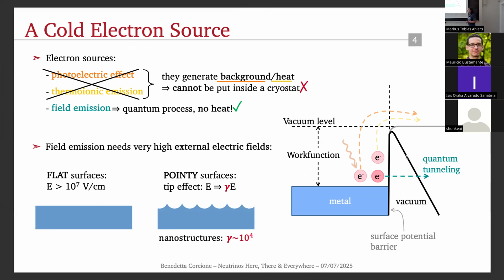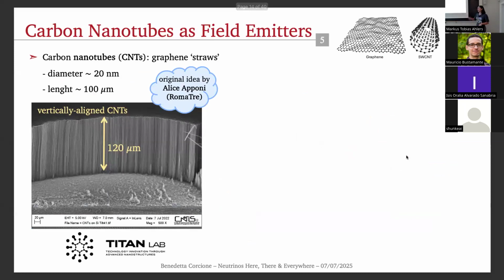So in particular, if we want to extract electrons from a flat surface, we need fields higher than 10 to the 7 volts per centimeter. But if we use pointy surfaces, so surfaces with some nanostructures, we can have some local field enhancement factor due to the tip effect up to 10 to the 4. And this is precisely the trick we use, because like that we can extract electrons with much lower electric fields. And the nanostructures we decided to use as field emitters are carbon nanotubes.